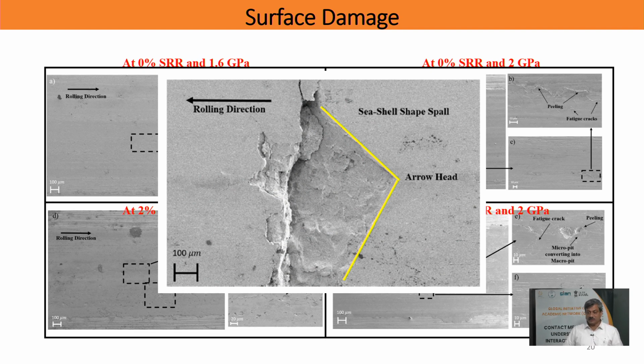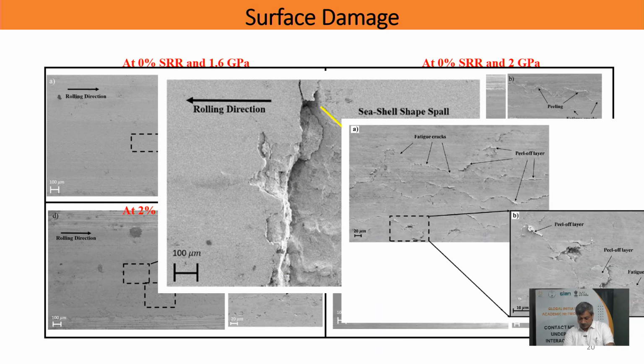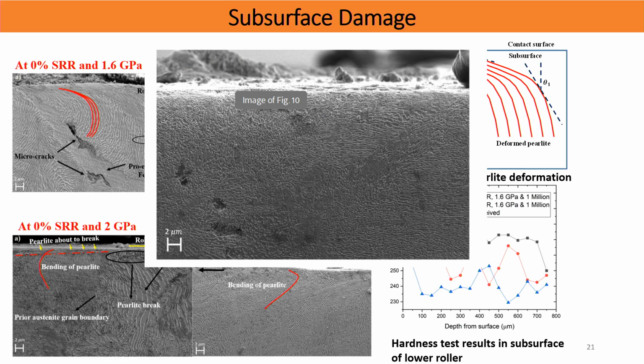Cracks form under the surface for many reasons. It can be inclusions, it can be grain boundaries, we'll see that. And those cracks can join up, and then you'll get a big pit, and spalling will start happening. So these are the kind of cracks which we are seeing here.